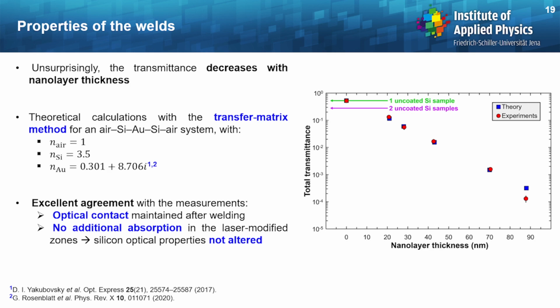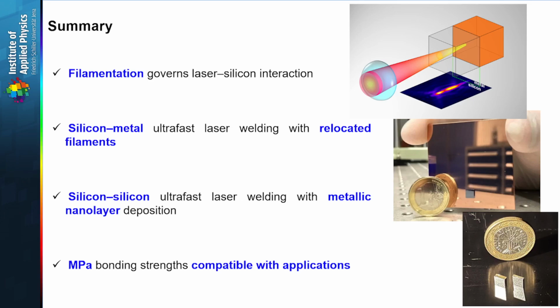And this means two things. First, the optical contact is still maintained after the laser processing. And moreover, and more interestingly, there is no additional absorption which would be related to the laser modified areas. In other words, the silicon optical properties are not heavily altered in that case. And with this, I would like to conclude my talk.